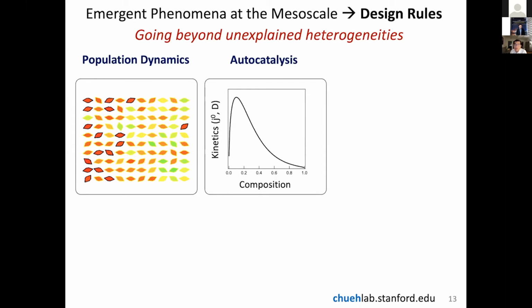The second theme is another interesting phenomenon called autocatalysis. For those of you who have a chemical engineering background, you will be familiar with this word. Autocatalysis means a catalytic event that speeds up as it proceeds. And it turns out for electrochemical ion insertion, it has an autocatalytic property. Because you're changing the composition of the material, inserting or removing lithium or other ions, as you insert them and remove them, the kinetics actually change dramatically. This is just a schematic showing, for example, the diffusion coefficient of lithium can change widely as a function of composition, several orders of magnitude. And this autocatalytic behavior also can explain and account for some of these unexplained heterogeneities.